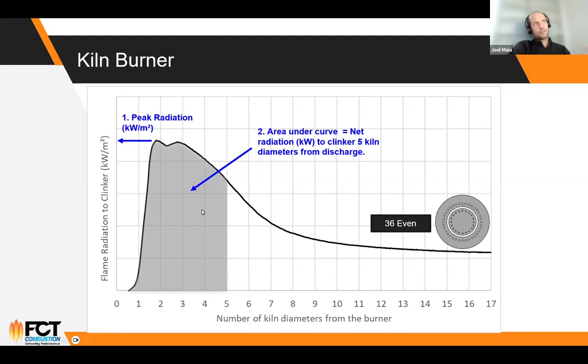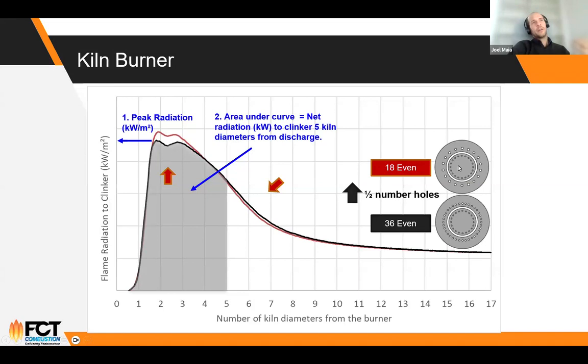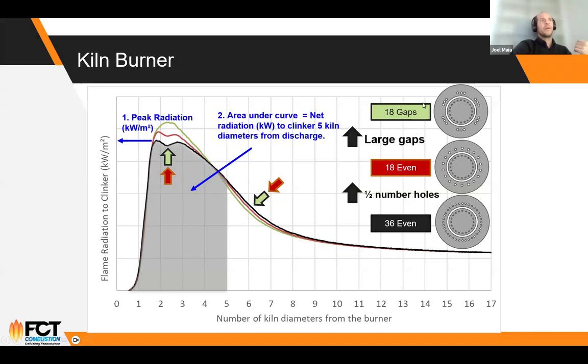If we look at this chart, this is the typical burner. We compare it to the burner with larger holes in a smaller quantity. We can see that the peak radiation increases, and the flame, after the clinkerization zone, gets colder, so the flame is a little bit shorter. And when we compare this to the next option, grouping the orifices 3 by 3, we can see a further increase in the radiation and a further reduction of the flame length.